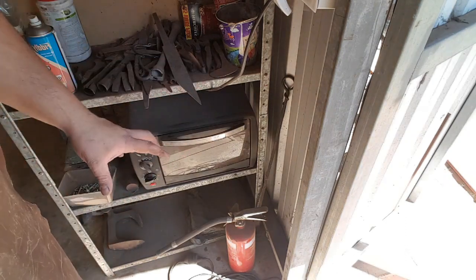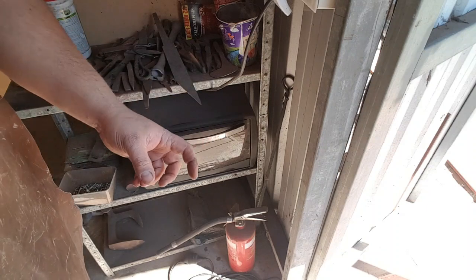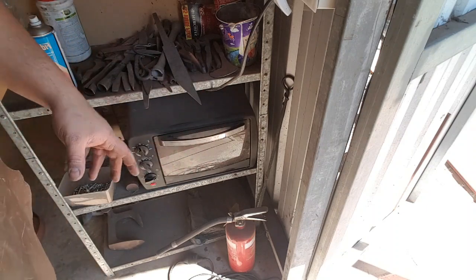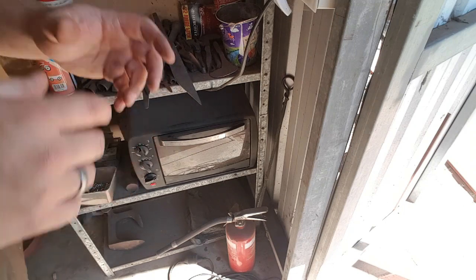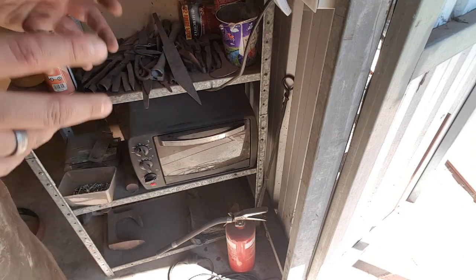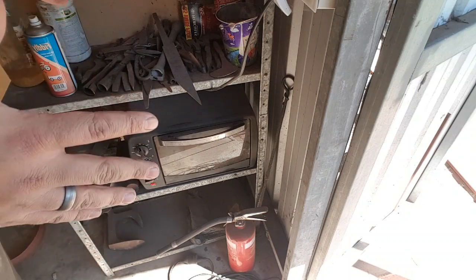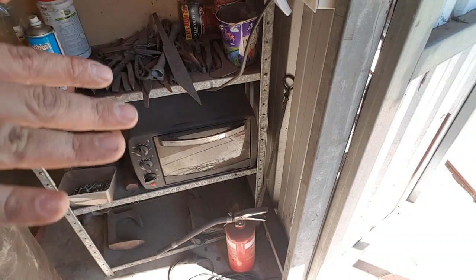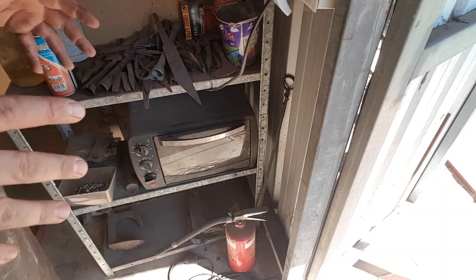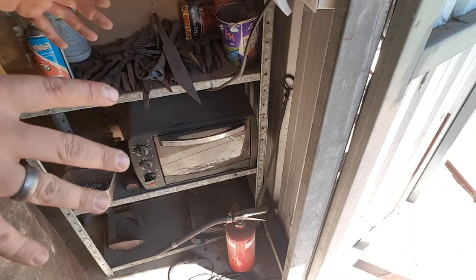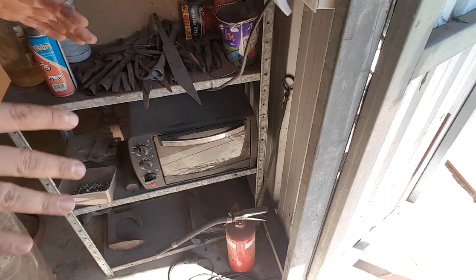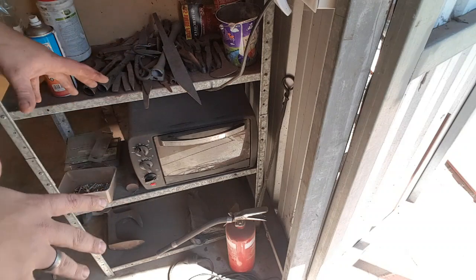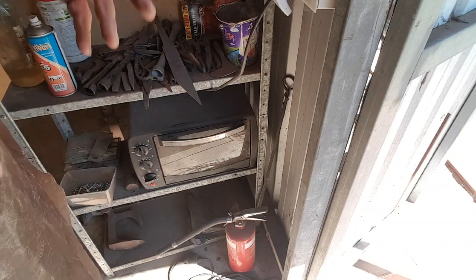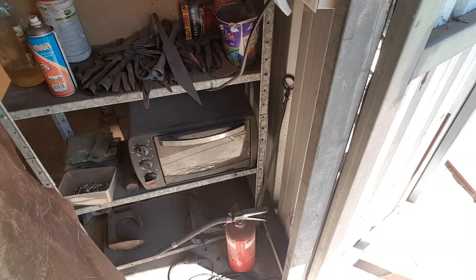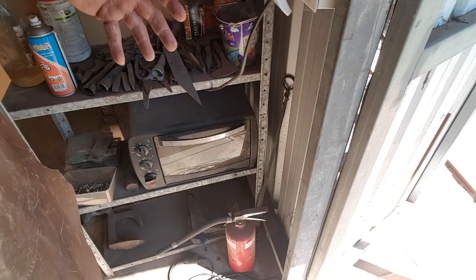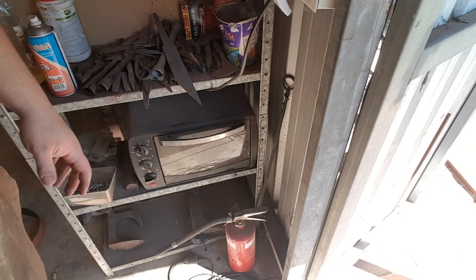If you want to get a better, more even heat on especially very thin pieces which you worry might unevenly heat in your oven, put it in a tray of sand. Just get some normal play sand or normal backyard sand, as long as there isn't wood and stuff in it so it doesn't burn. And then stick your piece on top of the sand or in the sand and heat it for that 2 hours, and the sand will act as a heat sink for the temperature and actually even it out a lot better. I'm not particularly worried about that in this case, but it's a really good technique if you've got especially large blades which might sit in different positions in your oven which may be uneven, because a lot of home ovens tend to be very uneven heaters.